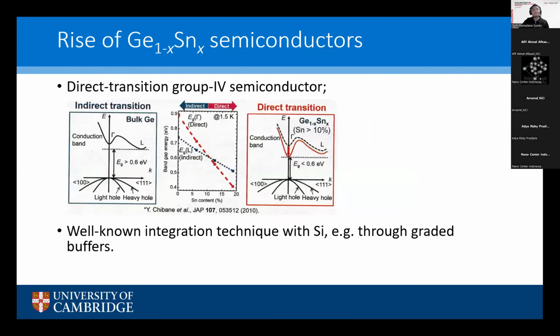Okay, so this perspective proposes a combination of all group 4 materials, germanium and tin, and silicon, to create the same concept we have for 3-5 semiconductors, similar to the indium gallium aluminum arsenide system. Basically, to be able to control the lattice parameters and the band gap independently by altering the chemical composition.